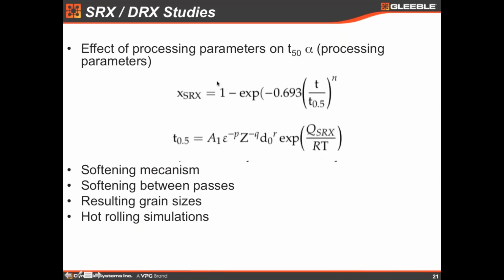I mentioned this is again, let's say, the hot deformation. We have static and dynamic recrystallization studies, and this is the sigmoidal curve equation as derived by Kolmogorov, Avrami, Johnson, and Mehl. And we can see here a new term. Instead of time, we have time divided by the time for 50% recrystallization.